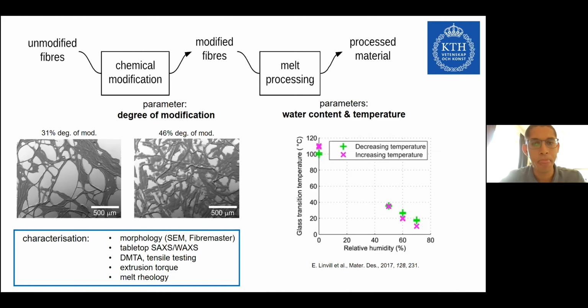modification. The modified fibers will then be melt processed, and there we will control parameters such as water content and the temperature of processing. We know that the water content of this material has a major effect on the glass transition temperature. And so with higher water content, the Tg is reduced. And so we would like to find some kind of optimum water content and also good temperature at which to do the processing. And once we obtain the processed material, we will also do characterization.